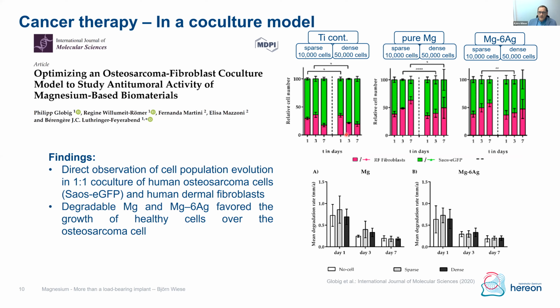And what he found out is the control seems to be not good. So the number of cancer cells increases with time after 1, 3, and 7 days, independent of the amount of cells he seeded on it.